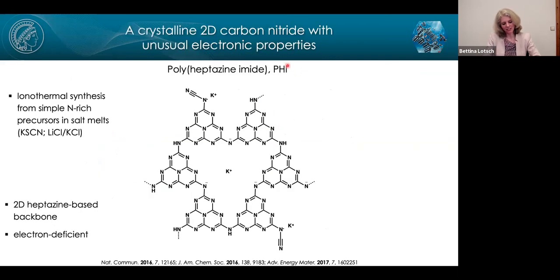And so the system that I will be talking about now is polyheptazine imide, PHI. So this is a two-dimensional system. So just imagine that this is a fully condensed in the plane, fully condensed heptazine-based system. And this is one of the few truly two-dimensional carbon nitrides. The typical carbon nitride that is simply and loosely termed C3N4 or graphitic carbon nitride is actually a one-dimensional heptazine-based polymer that was synthesized for the first time by Justus von Liebig about 200 years ago, and was called melon. For no obvious reason. So keep in mind that this one-dimensional carbon nitride polymer is called melon and is basically the benchmark carbon nitride, also the one that we compare this two-dimensional system to.